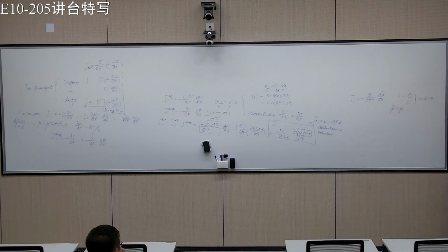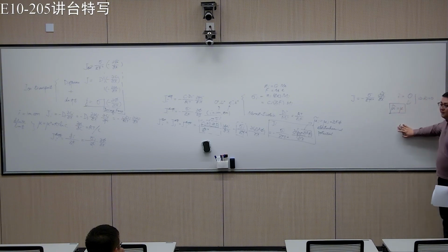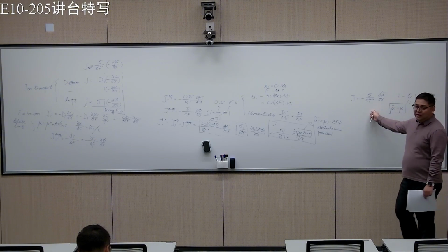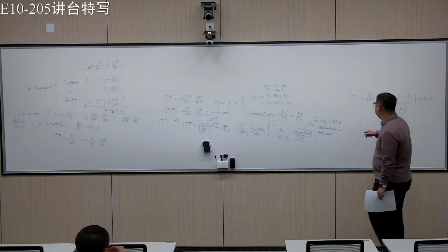Then mu tilde should be just mu, which means that for any charge neutral species, the electrochemical potential is the same as the chemical potential. So you cannot drive the motion by using the electric field. Then this should reduce to Fick's first law. Let's see if that's the case.